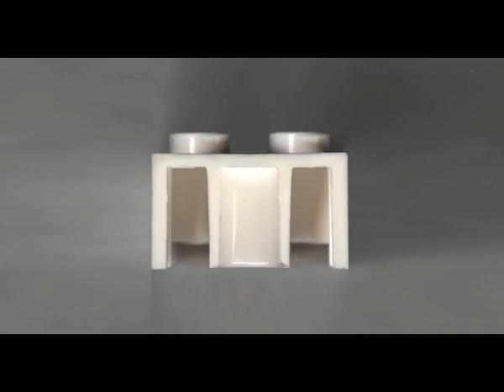So if you cut a Lego brick in half, you can see that these inner supports are thicker at the top than at the bottom. There's a draft angle of about one and a half degrees. This helps the ejector pins push the brick off the mold.